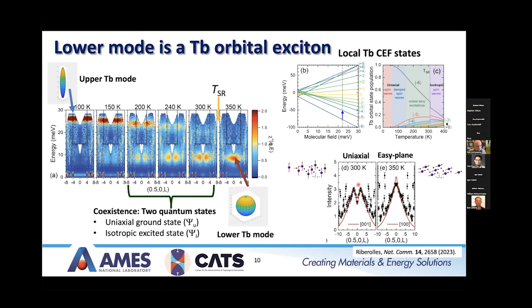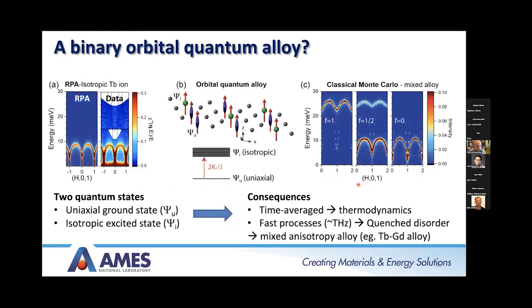So this intermediate regime is an interesting regime that Rob has come up with an interesting name for, calling it a binary orbital quantum alloy, where you can map this coexistence into what you would expect if you had some kind of mixed alloy. And you can show using some classical Monte Carlo simulations that you would expect the same kind of structure, the same kind of scattering pattern.